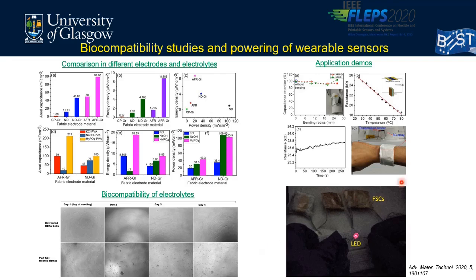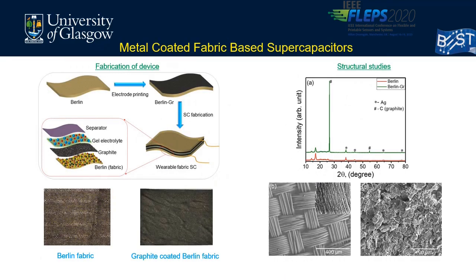Then, in order to show the practical utility of the fabricated devices, we have used them to power a temperature sensor based on the devices, like a wristband, and we can see the result of the powering of the temperature sensor. The mechanical stability of the fabricated supercapacitor with different bending radii also shows high capacitance retention under mechanical deformation. This shows the lighting of an LED with the fabricated supercapacitor.